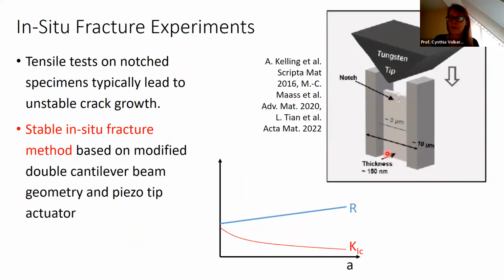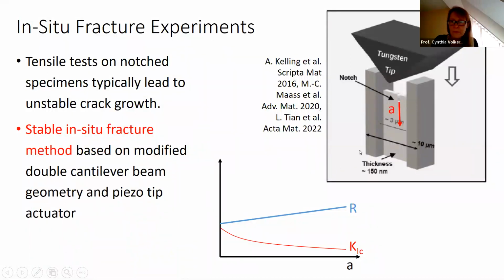This thickness will be around 150 nanometers. We're going to look through that with the electron beam. We cut a notch in this material, and then we come in with a wedge-shaped tip, and we pry these 2 cantilevers apart, causing then this notch to form a crack, initiate a crack, and to propagate down this lamella.